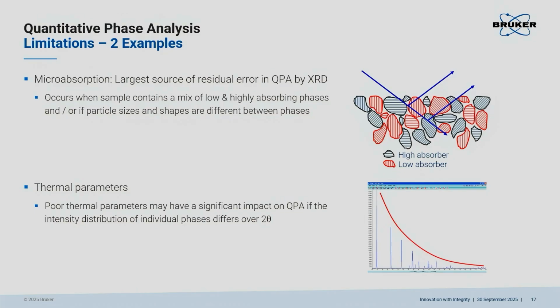The second error, which often goes through undetected, is incorrect thermal parameters. So you go into your structure database and, you know, for the quantitative phase analysis or your structural refinement, maybe you have your structure models, you have your coordinates, your space group, lattice parameters, and so on, and thermal parameters. But how would you know if these thermal parameters are correct? So many times you will find so drastically wrong thermal parameters, or even no thermal parameters at all. So what is your software doing then? Imagine you have structure data and there's no thermal parameters given, most software will then apply a default. They will set all missing temperature factors to 0, or to 1, or to 0.5. It depends on the software.